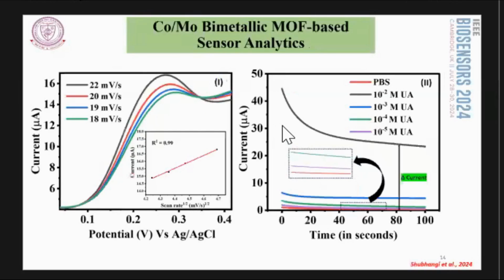Apart from that, a control study was also conducted where a scan rate dependent analysis was done in the presence of the target analyte, that is uric acid, in a concentration of almost 10 to the power minus 4 molar, where again we found a linear trend in the current and the square root of the scan rate, which stated a diffusion controlled charge transfer behavior even in the presence of the target analyte.